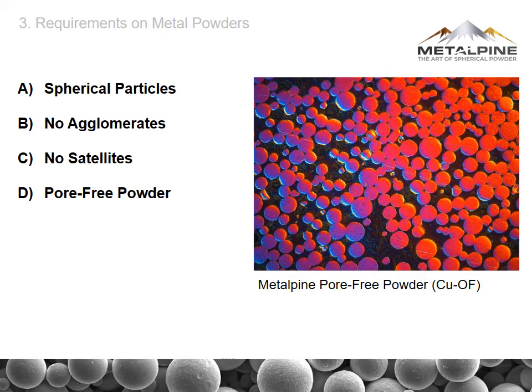At the end, you will also want to have pore-free powder. Above all, for pre-filming atomizers, a lot of pores or hollow spheres appear in the powder as there is really this thin melt sheet on the nozzle tip. The METALPINE process produces rather pore-free powder. You can see it here on the right.